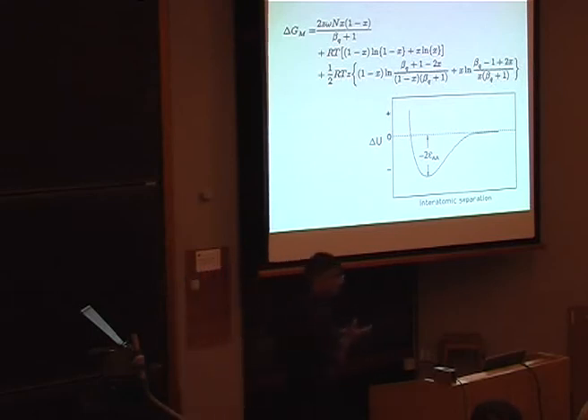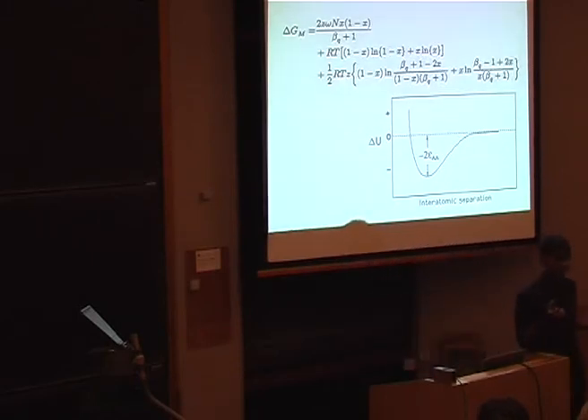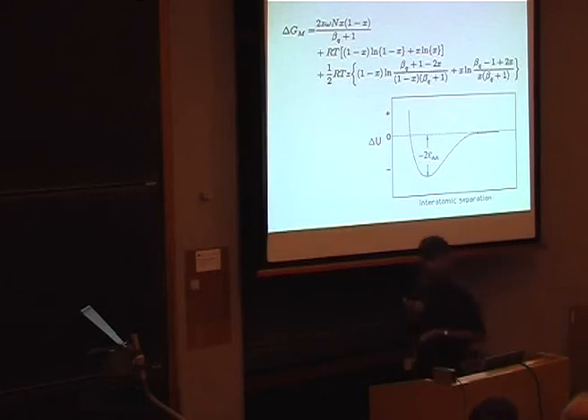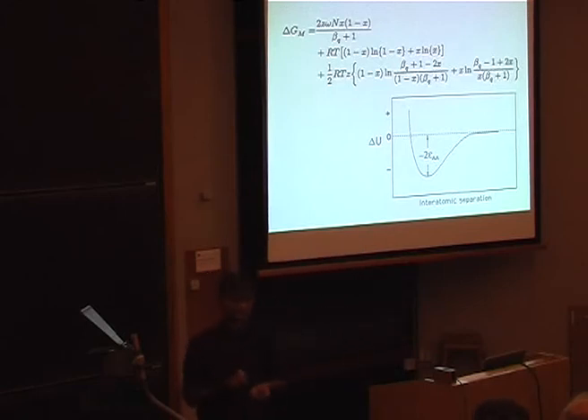Now, for austenite, you can measure that using thermodynamics, because the solubility of carbon is very high in austenite. But in ferrite, it's incredibly low. Very, very low at low temperatures. So we cannot actually determine it experimentally. We know that it should be strongly repulsive, okay? But we can't get a number.